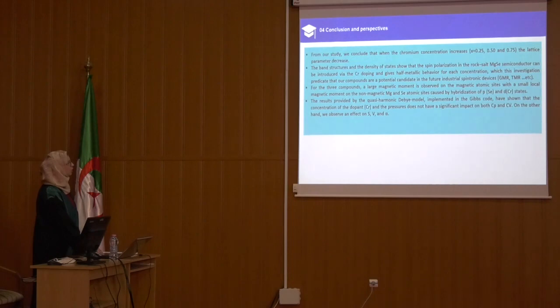The results, obtained with the quasi-harmonic Debye model implemented in the Gibbs code, have shown that the concentration of the chromium dopant and the pressure do not have a significant impact on either Cp or Cv. On the other hand, we observe the effect on S and alpha.